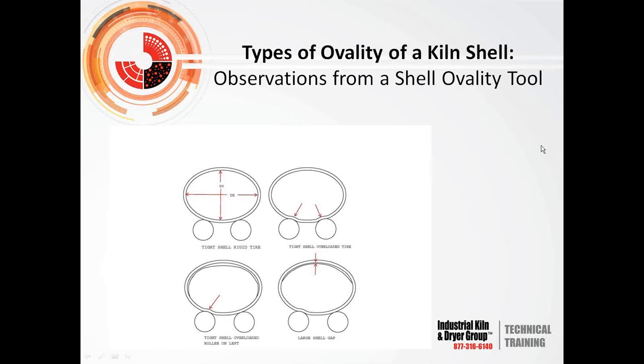Even though we're talking a little bit heavily right here on kilns, the one thing about all this movement and all this flexing of the shell that occurs even on dryers is what Roland previously mentioned about fatigue type failure and cracking that occurs in the shell. So even if you have a dryer and you have wrapper bands and thicker shell underneath the tire, if you get a lot of this flexing, you would see a lot of fatigue type cracking. Yeah, and John, even if it's a dryer, obviously we're going to slim down the tires and the rollers because of less load.